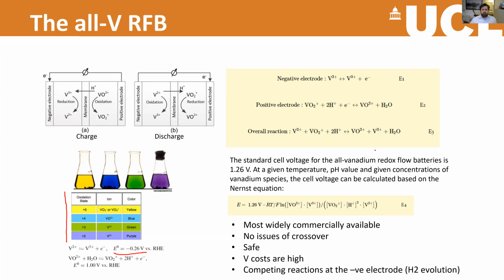And then offline, you can recycle or regenerate that electrolyte. So hopefully you don't have to renew the electrolyte, but you might have to. Other issues might be if you've got some leakage, for example, in your system over the operation of many years, that could be significant. Or if you have these competing side reactions, such as the hydrogen evolution reaction, that obviously depletes the amount of water you have in your electrolyte, and that can then also reduce the solubility of your species in there.